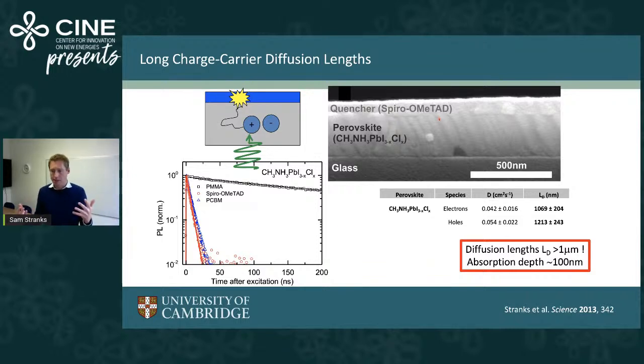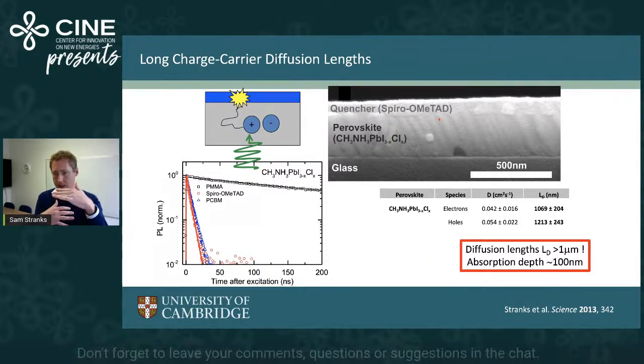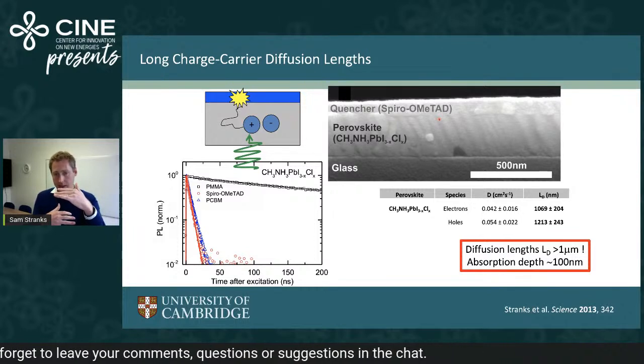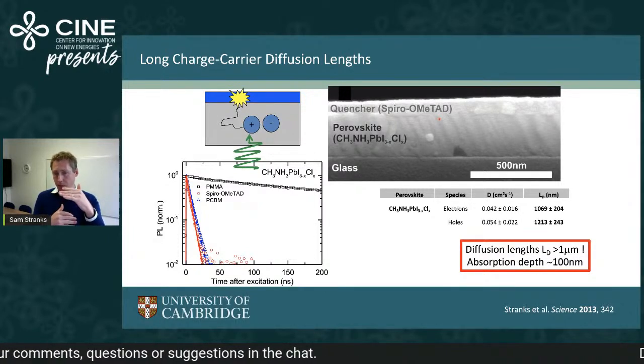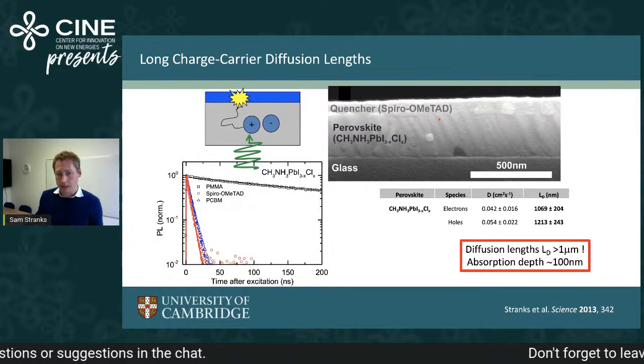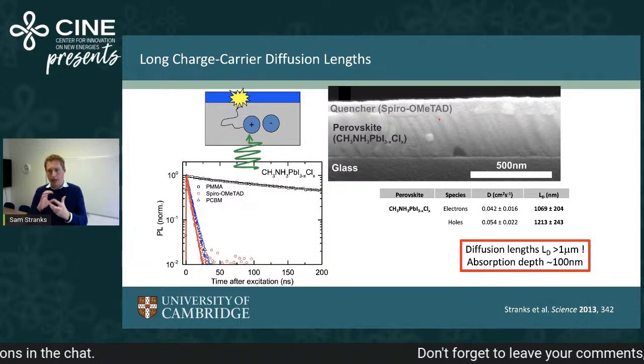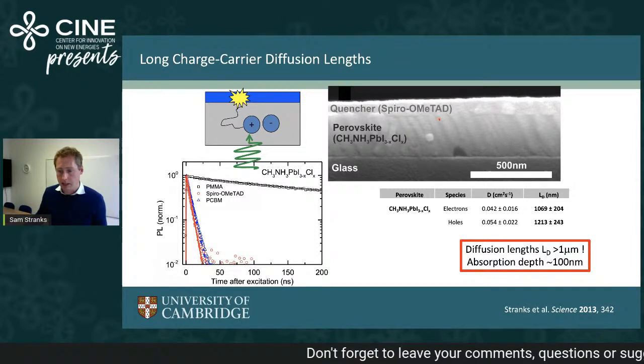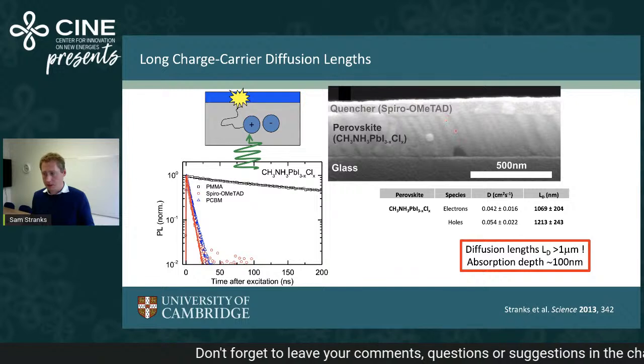And so this allows us to design the cell in a very easy way. We can sandwich just these electrodes between this absorber material. And it's a very simple, what's called a planar heterojunction architecture. We don't need to have more complicated collecting architectures, which inevitably lead to losses.